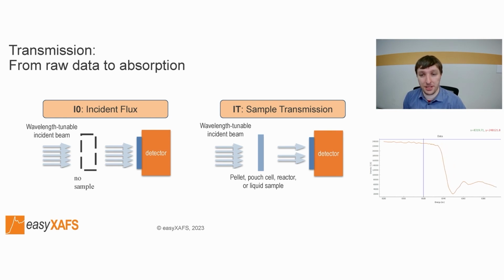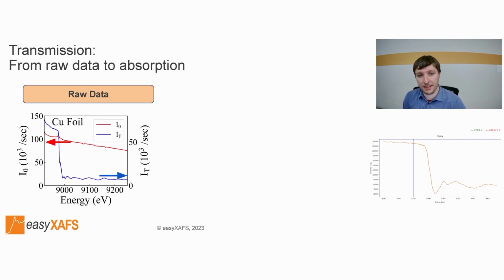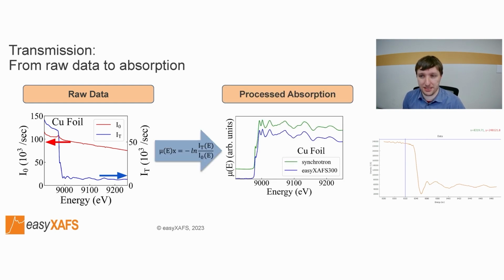In transmission mode, the incident flux is measured through an empty sample holder. We then collect the transmission intensity through whatever sample or setup we would like to study. Here we have an example of the I0 and IT data for the copper K edge of a copper reference foil. In contrast to the small changes in the I0 data, the IT measurement has a large drop in intensity resulting from the copper K edge absorption. We can then calculate the absorption spectra from the I0 and IT measurements using the natural log equation shown here.